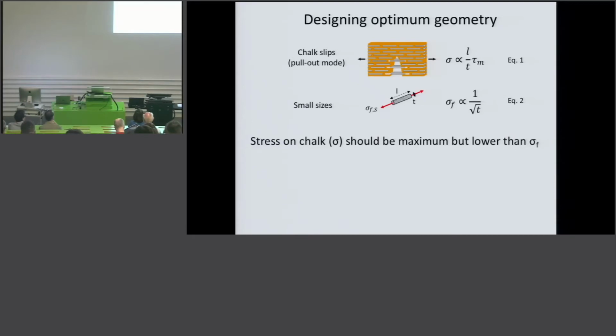All right, so what have we learned so far in terms of design? First, we want to make sure that we are in pull-out mode, but we also want that the platelets carry a lot of load. And so we learned this very simple relation, which shows how the tensile stress on the platelets correlates with the shear stresses that is being applied by this polymer matrix all around. And this correlates to this simple geometrical factor, which is the aspect ratio of our platelets. We also learned that it's good to be small, right? The smaller you are, the stronger are your platelets. And so, as I told you, the stress on the chalk should be maximized, but it should be lower than the fracture strength of our rods, right? So what does that mean?